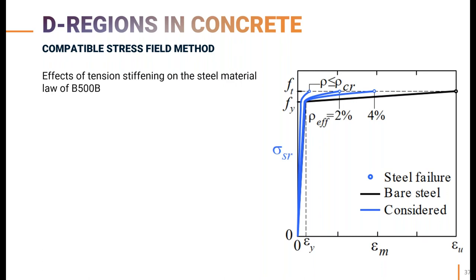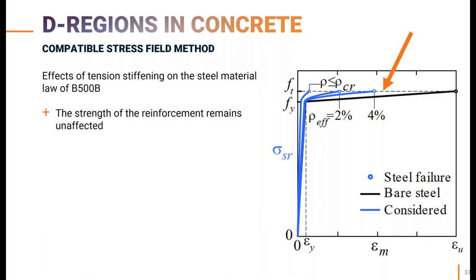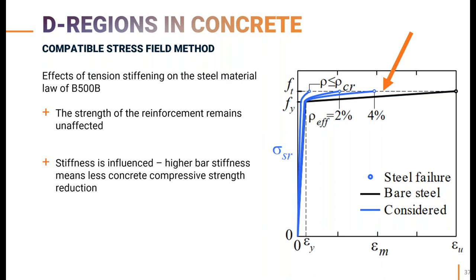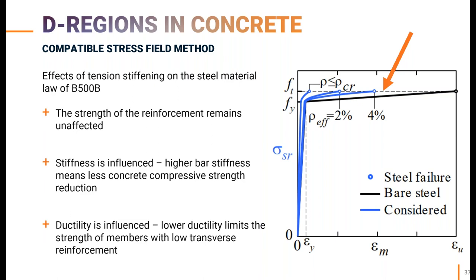So there are higher stiffnesses in cases where higher stiffnesses due to tension stiffening can result in lower transverse tensile strains imposed on the concrete in compression, and as such, they create a less pronounced reduction in the concrete compressive strength. Of course, the FT value is always respected in any case. Lastly, the reduction of the ductility of reinforcement may limit the strength of members with low amounts of transverse reinforcement. Since we're running out of time, let me jump into IDEA StatiCa, where I will demonstrate the use of the method.